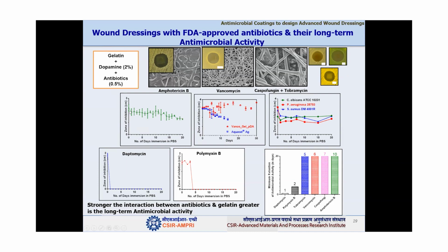We tried to immerse these wound dressings in PBS, and then tested their antimicrobial properties at different time points. We found that even after 20 days of soaking these dressings in PBS, these materials consistently have the antimicrobial properties. That means they are very durable wound dressing materials.